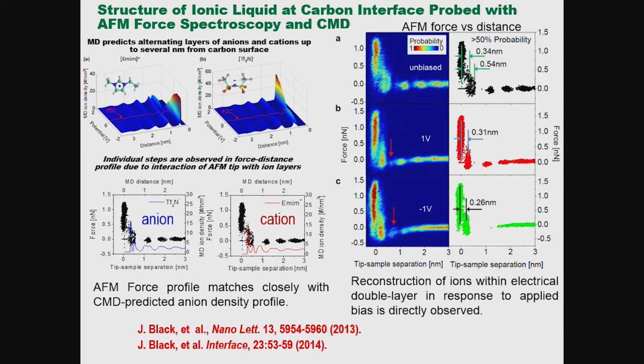This is HOPG graphite in this case, so very, very bulk graphite behavior. And still we see this nice layering, which is detected by force microscopy. And that changes as you go from positively charged to negatively charged interface. We can also computationally model that.